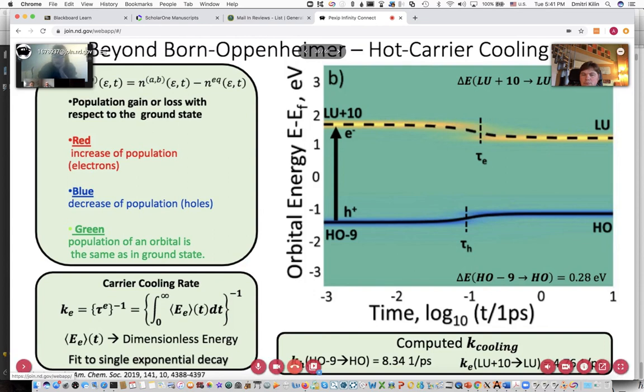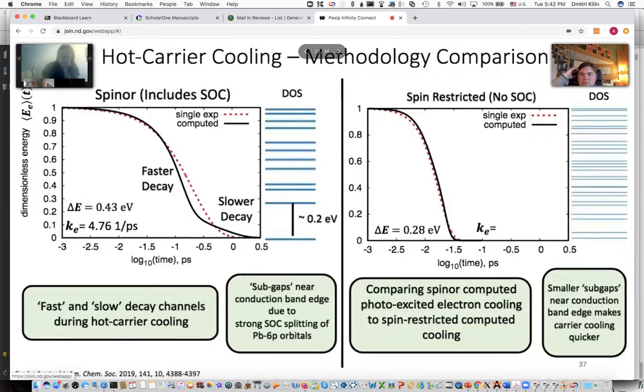And so essentially, for the electron and hole, we have energy decay. And then to get the cooling rate of the charge carriers, we fit the decays to a single exponential, which is this KE. And then for both the electron and the hole, their overall cooling dynamics are roughly the same order of magnitude. So it's 100 to 200 femtoseconds for the decay to their lowest energy states. If you look closer at the electron decay, it does show a little bit more vibrational relaxation dynamics than the hole.